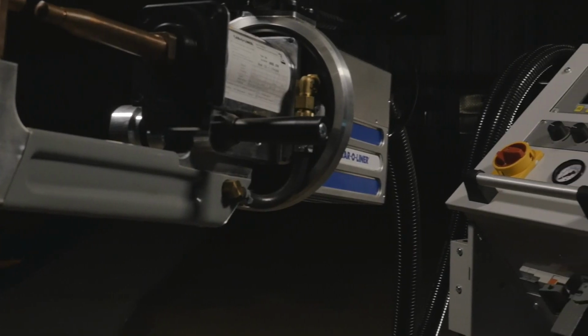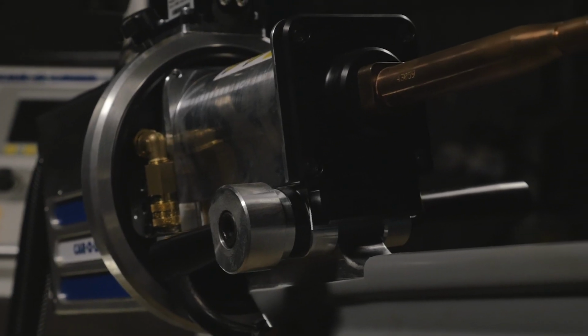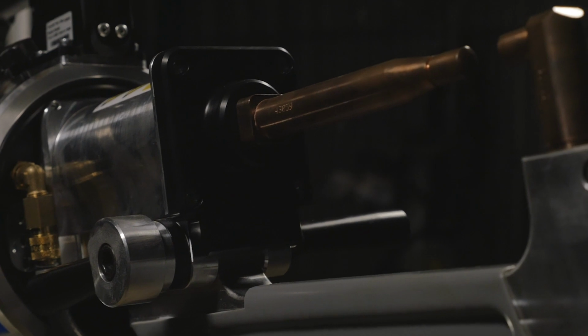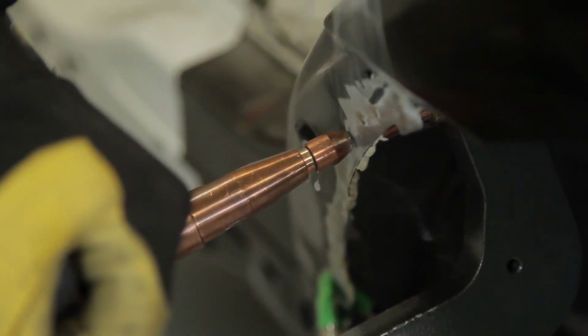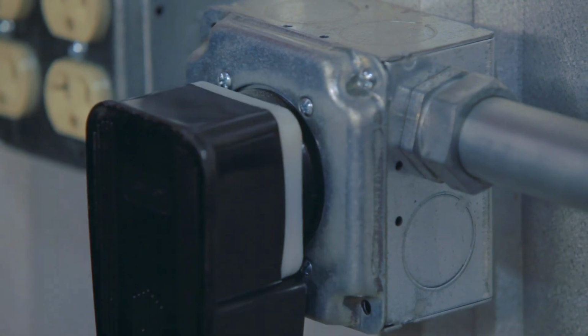As I mentioned, spot welding has really become an essential tool for collision repairs. If we're not spot welding on today's vehicles with all the high and ultra high strength steels found on them, we simply aren't repairing the vehicle properly. If we're using conventional plug welds on an ultra high strength steel part, we are damaging that steel, and we may be compromising the structural integrity of the vehicle, the crashworthiness of that vehicle. So using a squeeze type resistance spot welder is absolutely an essential tool. And you may need to make sure, as they covered in the show in September of 2018, that the facility's got adequate power to make sure that the machine works, because the best machine in the world won't perform as designed if you don't have the proper power at your facility.